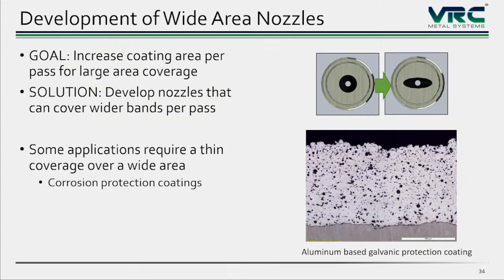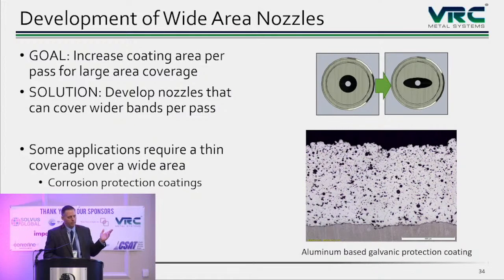Okay, so that's my materials part of it. I'm going to talk about equipment now, a couple of equipment developments. One is in nozzles. This was a project looking at applying coatings to large surfaces. So if you want to apply a corrosion inhibiting coating, like a galvanic protection, for instance, to a large surface, how might you do that? Well, we know that cold spray has a very constrained plume, which is nice for us when we're trying to repair parts. It makes masking a lot easier and so forth. However, when you want to coat a large area, having a very constrained plume means you have to have very high accuracy of your path planning and so forth. So if we go to a wide area nozzle where we can spread that plume out a little bit, that'll make coating large surfaces easier.